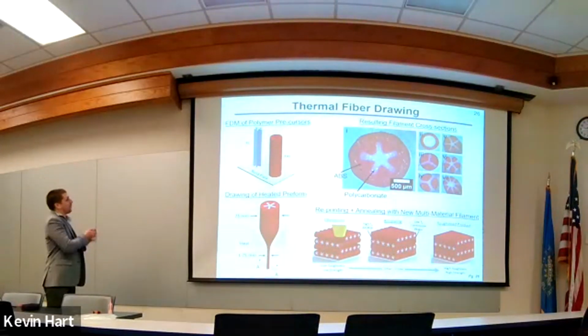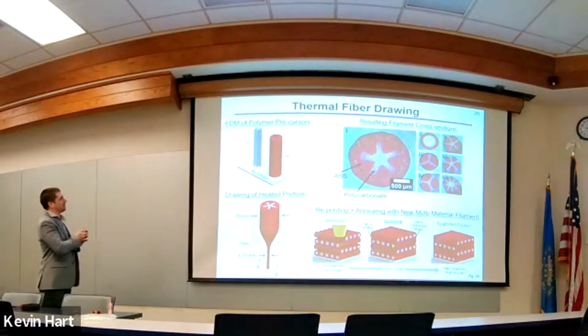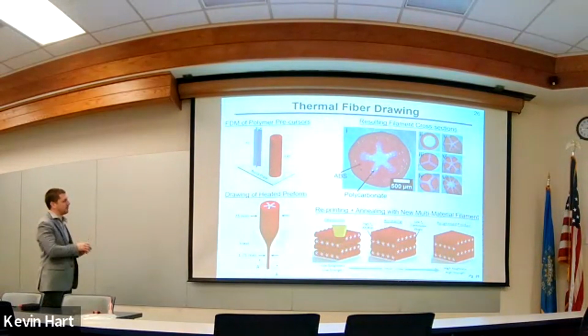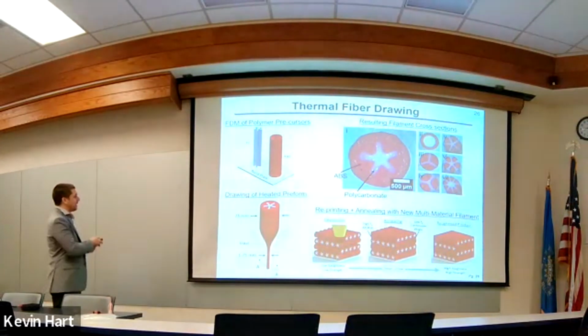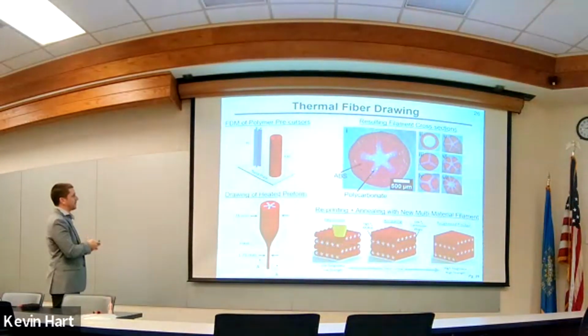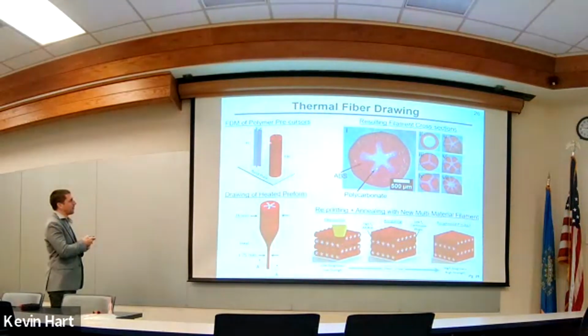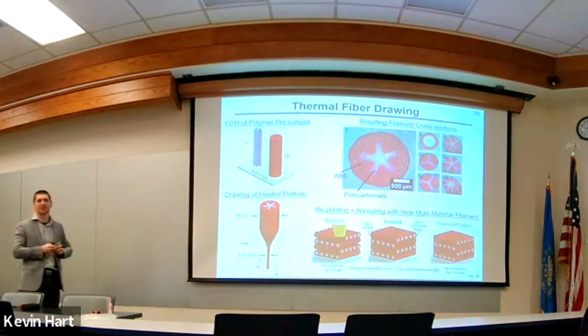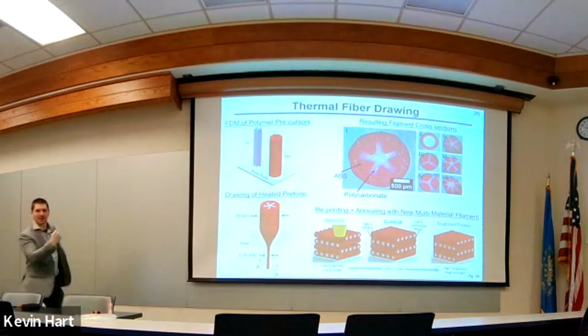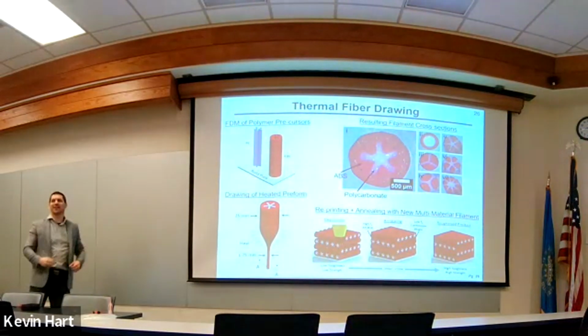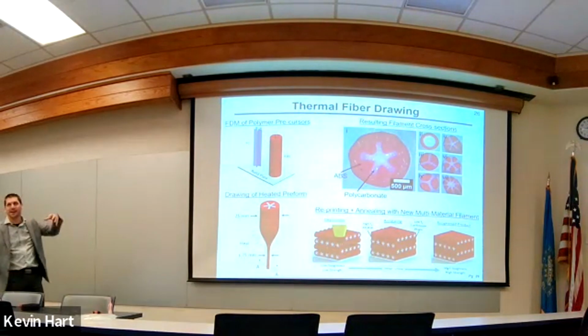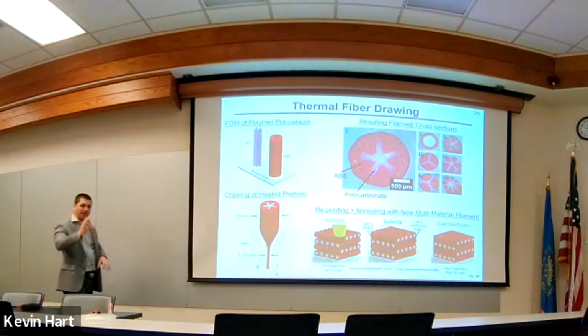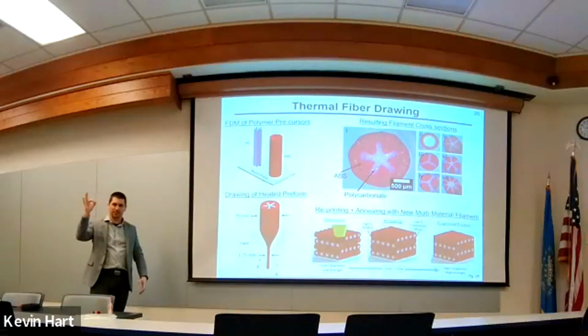All right. So how are we going to make these filaments? Here's the process. I'm printing an ABS, what I call a preform. It's maybe 1 inch in diameter. And I'm going to print polycarbonate separately. That's going to be the core that goes inside of the blank ABS. Then I'm going to take my arm and push them together. So I shove the polycarbonate into the ABS, and I have maybe a 1 inch diameter, what we call a preform.